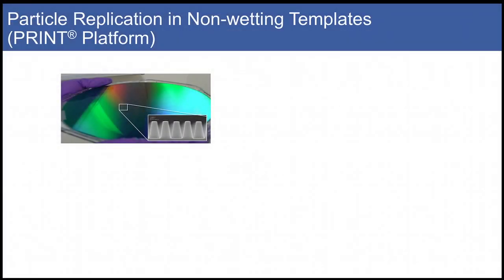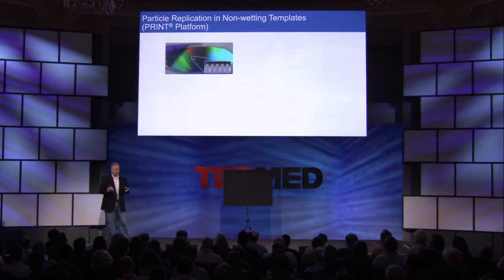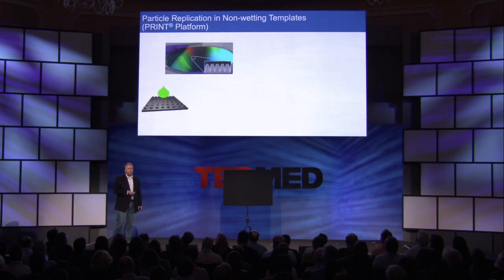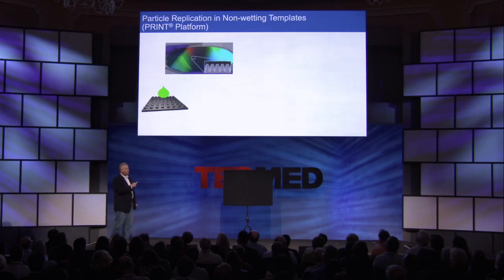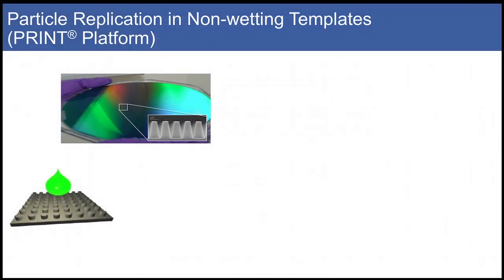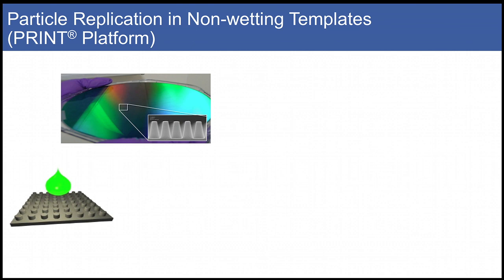Basically it's a molding technique. We lithographically define or etch features into a wafer — these are 100 nanometer features. To put this in context, a red blood cell is about 8,000 nanometers in diameter. My group developed a material we call liquid Teflon — it's like a silicone oil, but highly fluorinated and non-stick like Teflon. We pour it onto this patterned wafer, and it wets every nook and cranny at the nanoscale. We shine a light on it and peel off a mold or membrane that represents with very high fidelity the features in that silicon wafer.